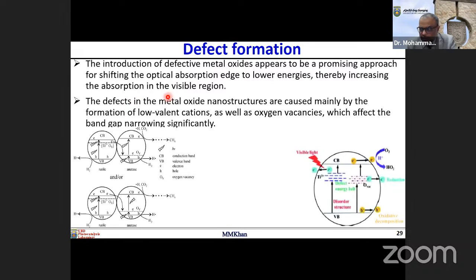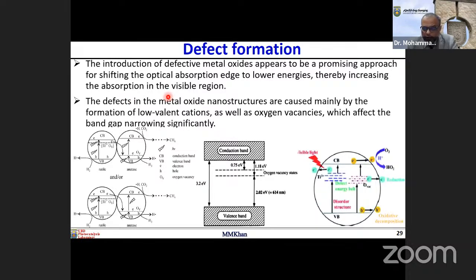So you can see here, we can form different types of defects. For example, you can see the oxygen vacancy defect, or even the formation of low valent ions. The defects in the metal oxide structures are caused mainly by the formation of low valent cations. For example, here, this is titanium oxide. In titanium oxide, titanium is here the Ti3+. So that is the low valent ion. Or we have different oxygen vacancies. So if you have a pure material and you create defects, sometimes the material will become responsive. So that is the advantage of defect formation.